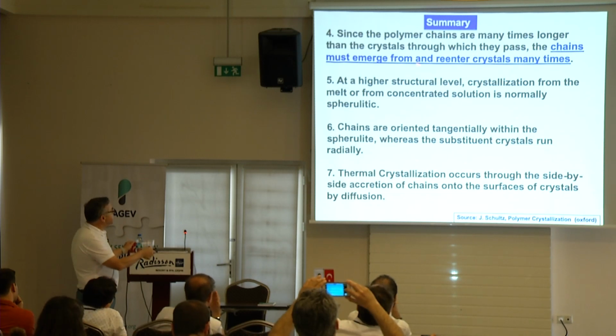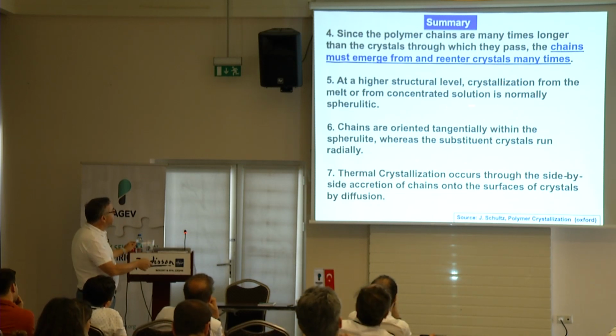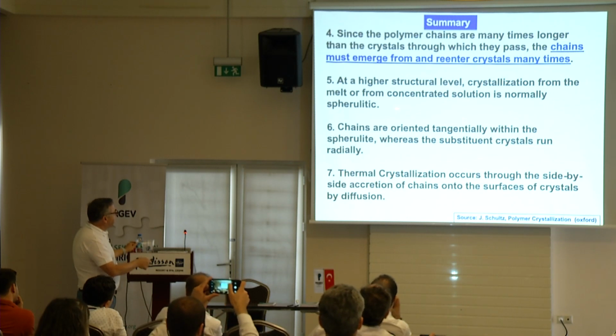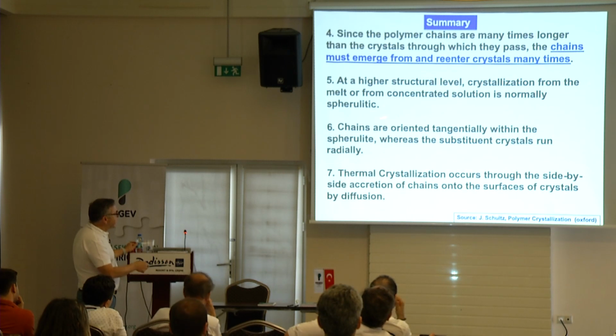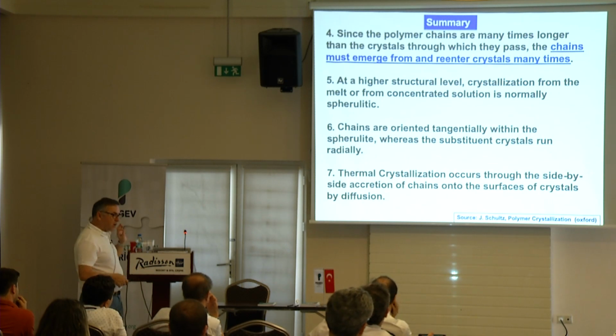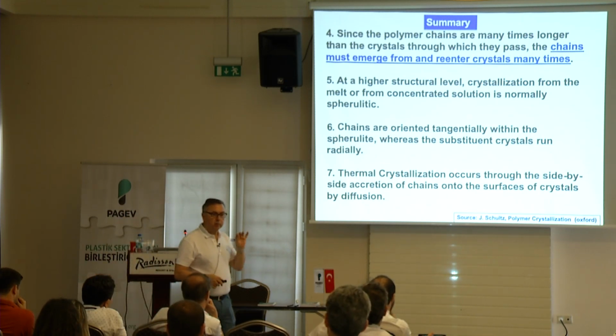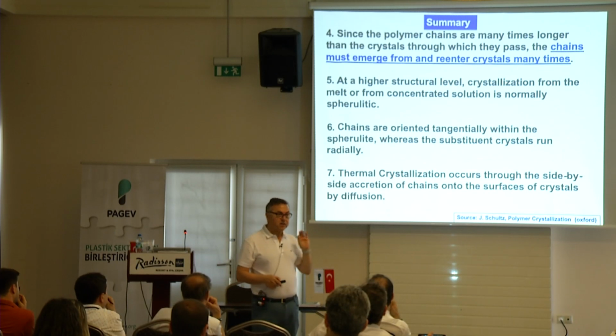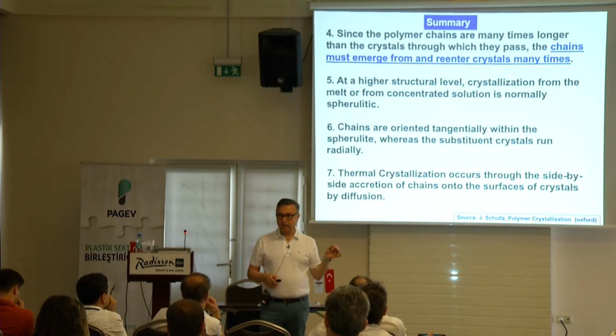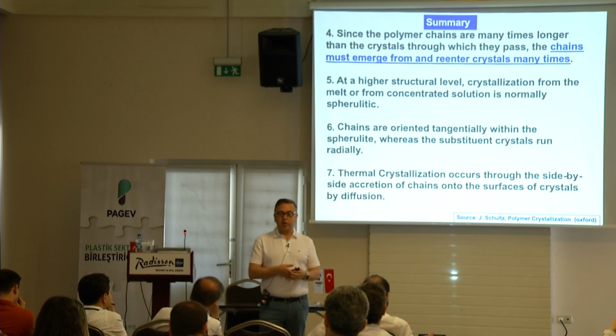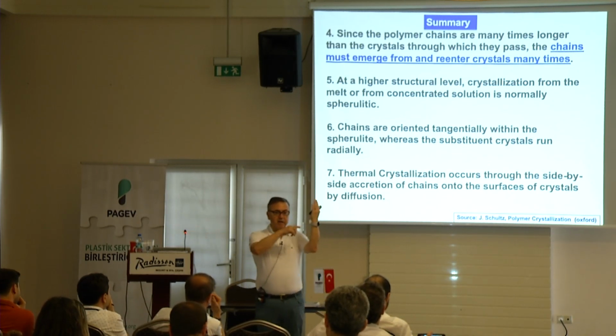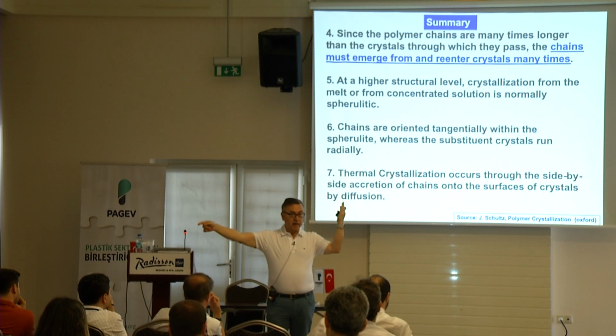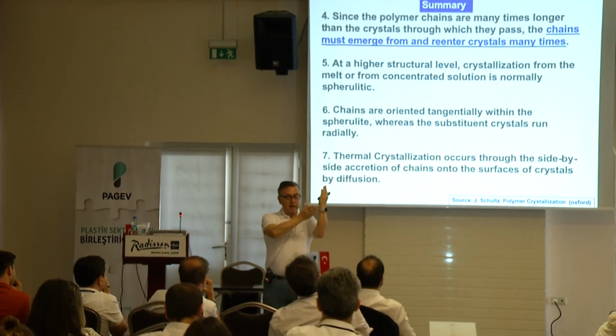All right, I said that this is about stitching that I told you. And typically under quiescent conditions, you always get spherulitic structure, and chains are always tangentially oriented. Now what I have shown you is what we call a thermal crystallization. We haven't talked about stress crystallization. Thermal crystallization involved polymer chain going to the interface, as you saw, and in order to get there, it has to diffuse through other chains and then grow.